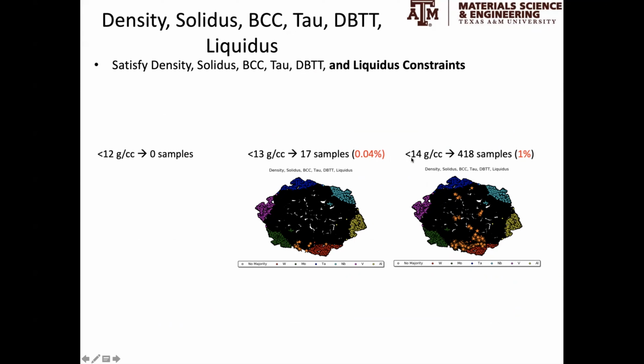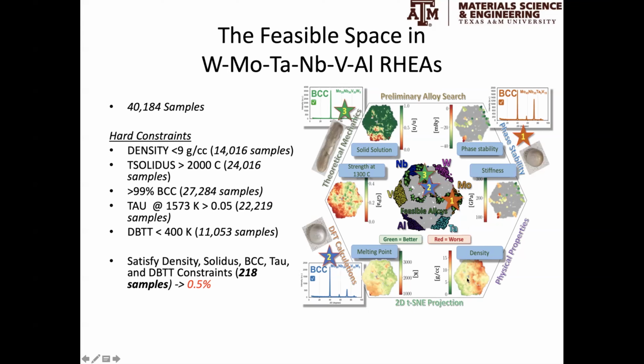When we put everything together, this is what we find - a collection of all the different constraints we were looking at when trying to quantify the feasible space in this problem. We actually picked 3 alloys at random, and our experimental colleagues were able to make them and verify that they were 100% BCC, as we had predicted.